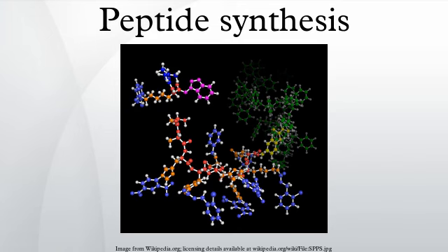Since then, new resins have been developed with the following advantages: enhanced swelling or rigidity, and chemical inertness. Highly cross-linked polystyrene has been developed that possesses the features of increased mechanical stability, better filtration of reagents and solvents, and rapid reaction kinetics. Polyamide resin. Polyamide resin is also a useful and versatile resin. It seems to swell much more than polystyrene, in which case it may not be suitable for some automated synthesizers, if the wells are too small.